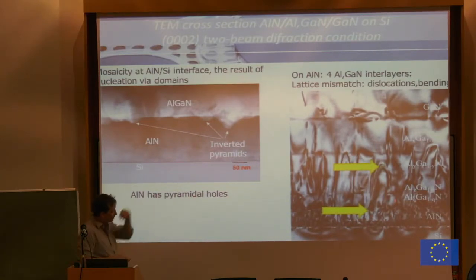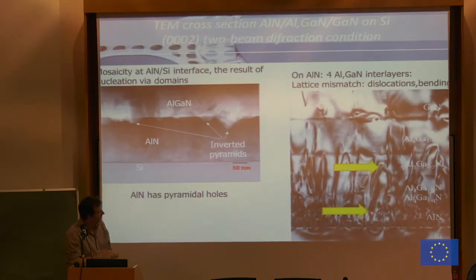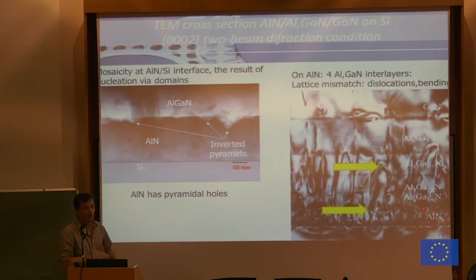I will focus on this one here, which is a cross-section TEM of a typical AlGaN stack on silicon. So we start with aluminium nitride of very poor quality, and you can see we then grow up with different AlGaN layers that have less and less aluminium as you go up in the structure. Here we obviously do hetero-epitaxy, so we grow aluminium gallium nitride on aluminium nitride, and you can see that the effect of the strain on the threading dislocation is that here at this interface where the strain is being built up, you bend your dislocation, and at the next one here it happens again, so it bends even further. And the advantage of this mechanism is that if you have two of them and they happen to be at the same place, they can actually meet and annihilate one another.